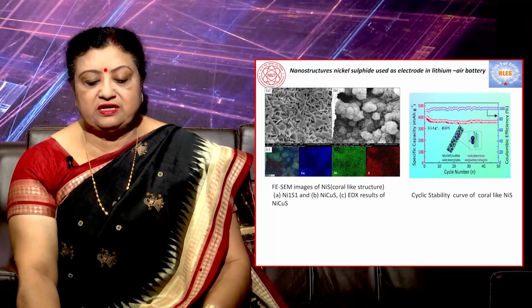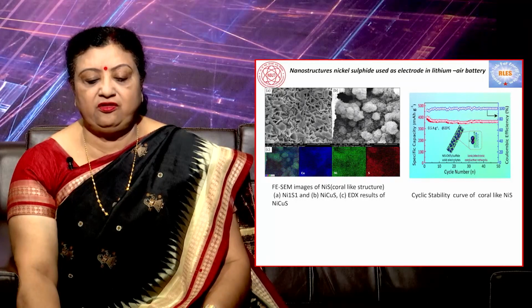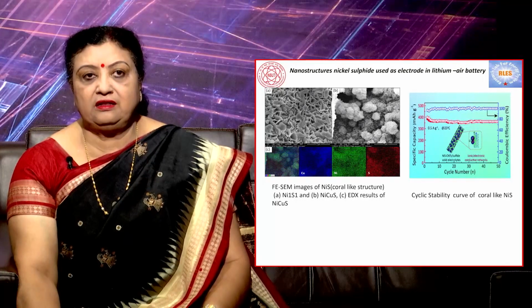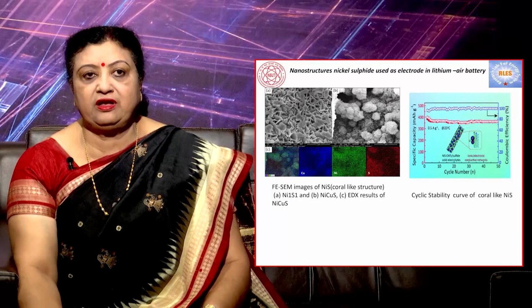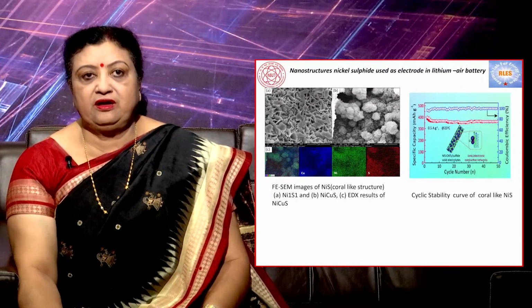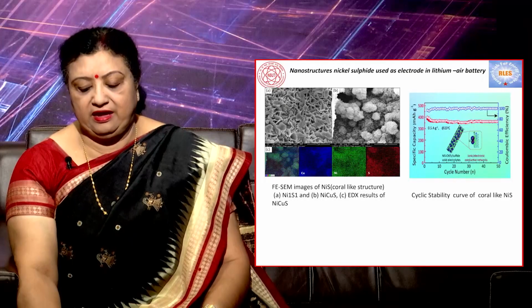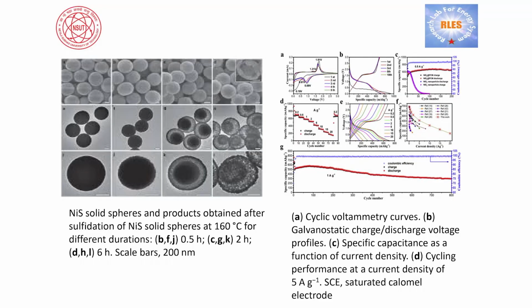and the different structures. The EDX result of NiS has been shown here, along with the electrochemical stability curve of coral-like NiS. NiS solid spheres, the product obtained after the sulfidation of NiS solid spheres at 160 degrees centigrade for different durations like 0.5 hour, 2 hours, 6 hours, and the scale bars are 200 nanometers.